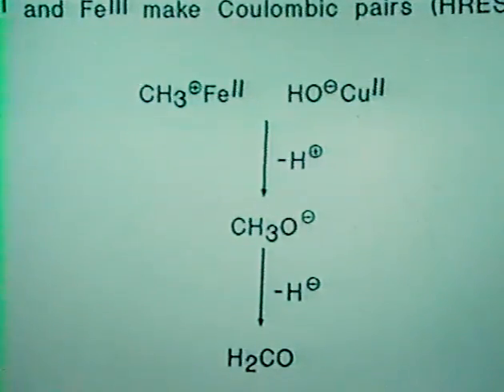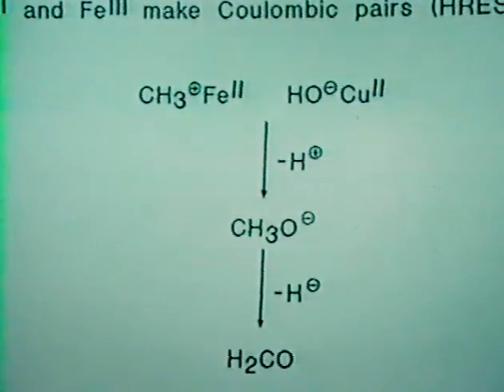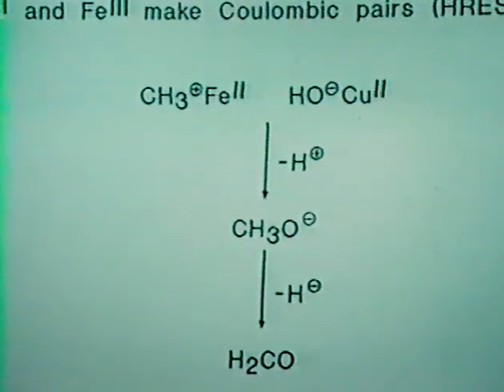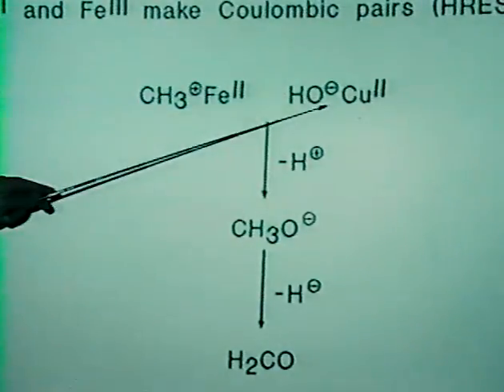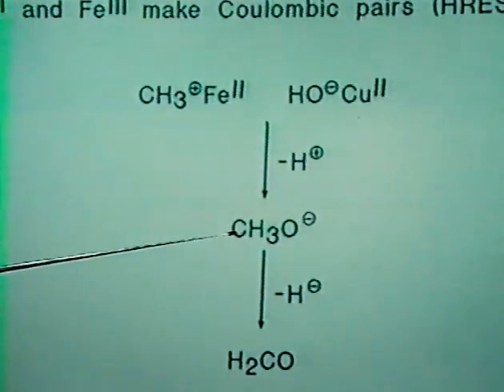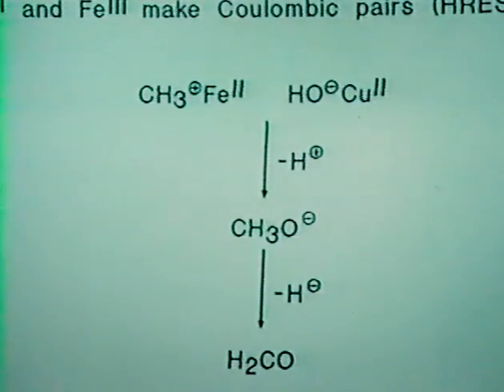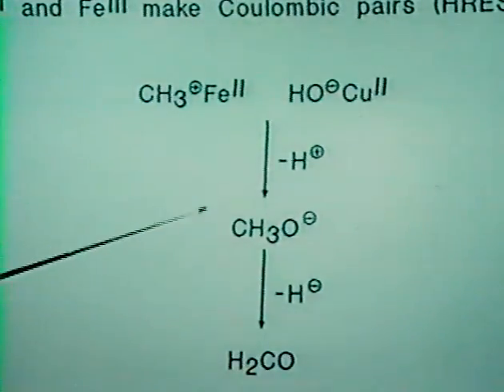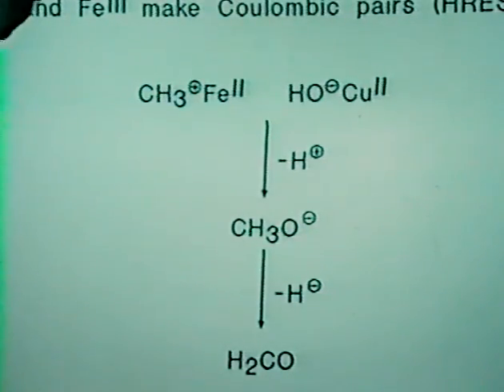The next thing is the mechanism, and as we know, the mechanisms are hard to prove, and one has to do a lot of spectroscopy, but this is how we think it works. We have the basic chemistry for making methoxide, and then in all the systems in which oxide catalyzed reactions form formaldehyde, we think, and I think most people think, that the precursor to formaldehyde is actually methoxide, and that formaldehyde is made by hydride abstraction. So you have to have a hydride acceptor, but Union Carbide had made a homogeneous methanol catalyst, which had copper 1, and they say it's a copper hydride. Copper 1 hydride exists, so there's no question about that.